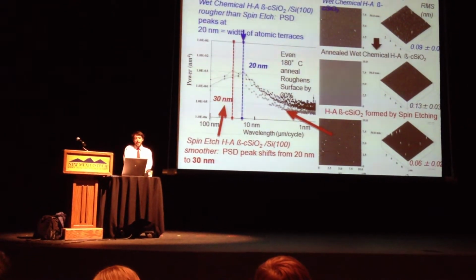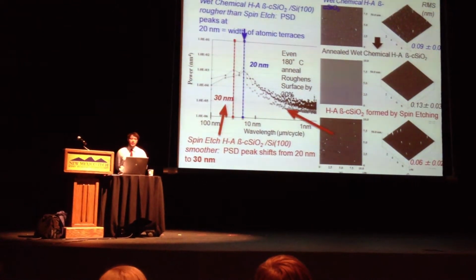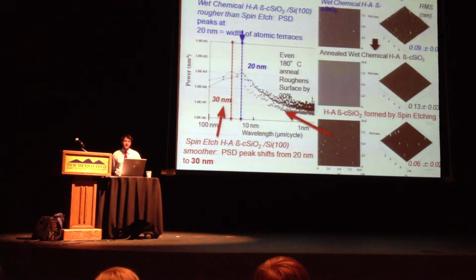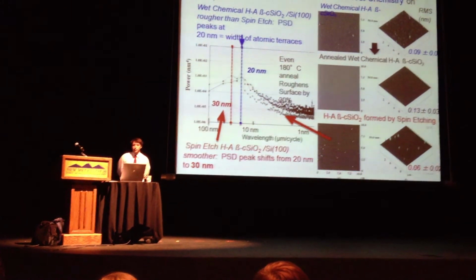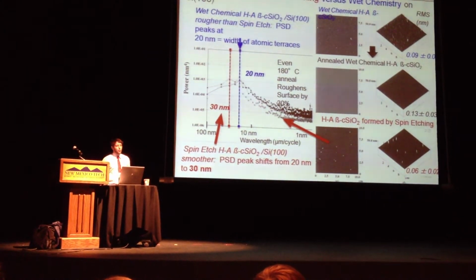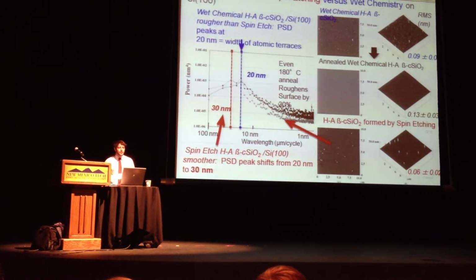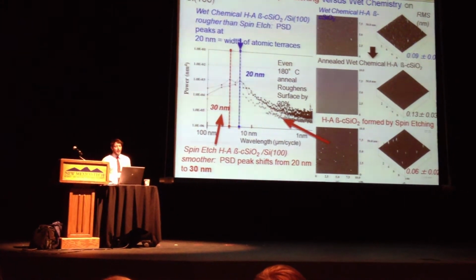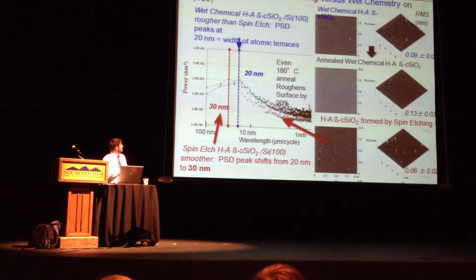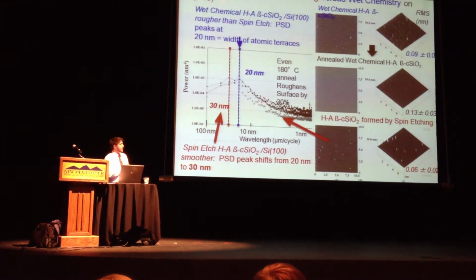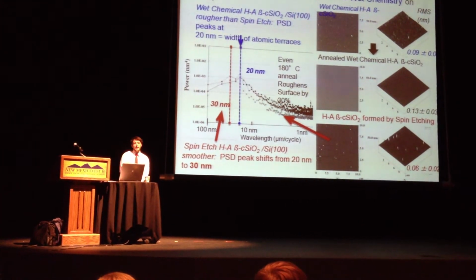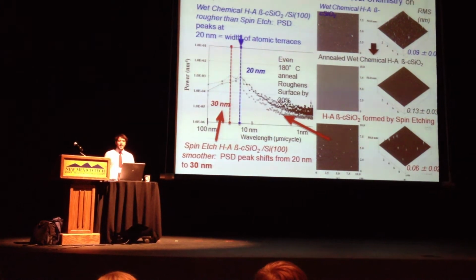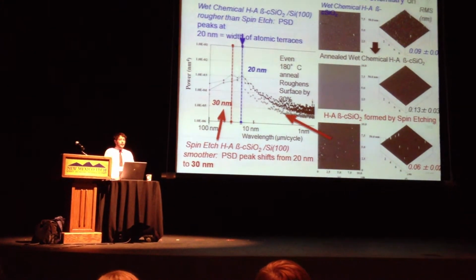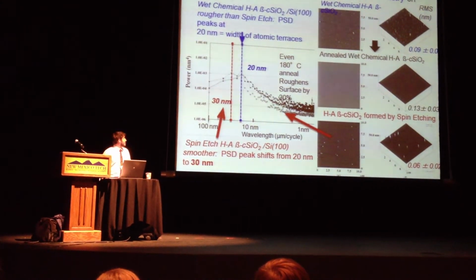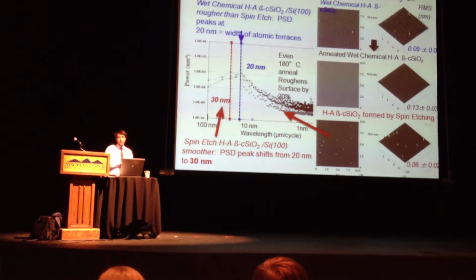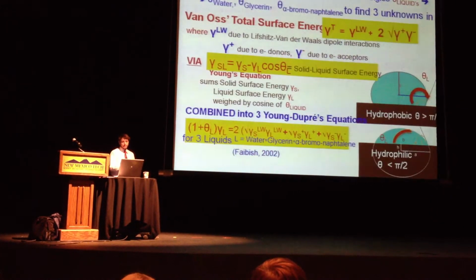Okay. And another technique that we have analyzed is the difference between a spin etch and a normal wet chemical bath etch, submersion. And we see that with the spin etch, we have a peak density of around 30 nanometers. So we are again increasing, instead of from 2 to 20 nanometers, we are increasing that terrace length to about 30 nanometers, which is a large improvement.